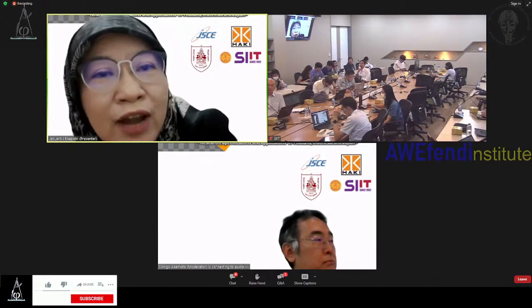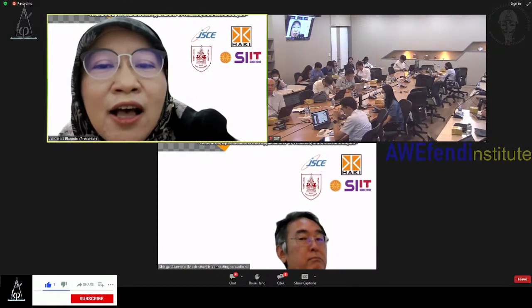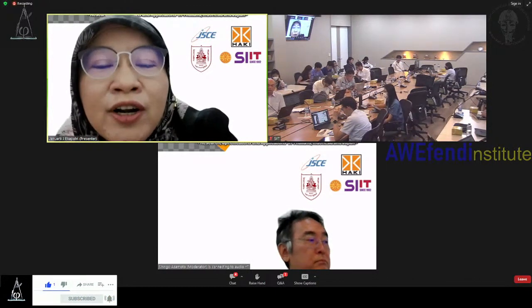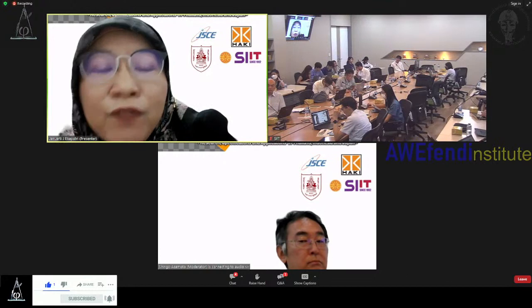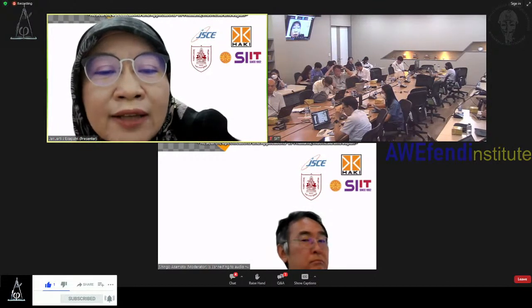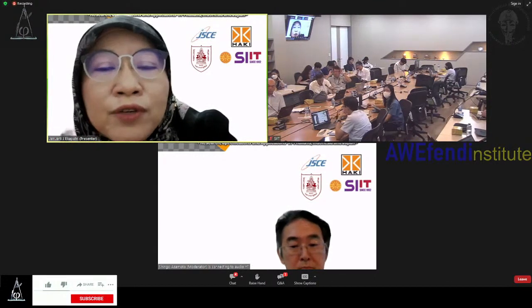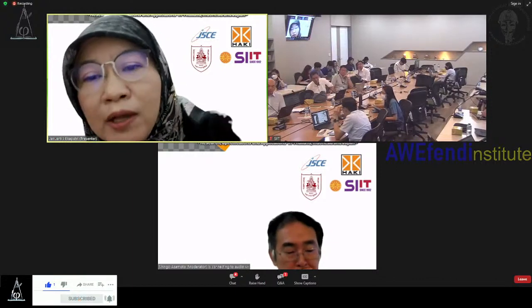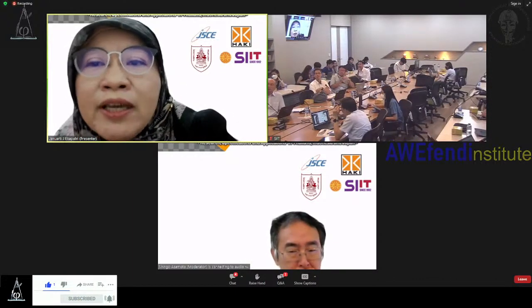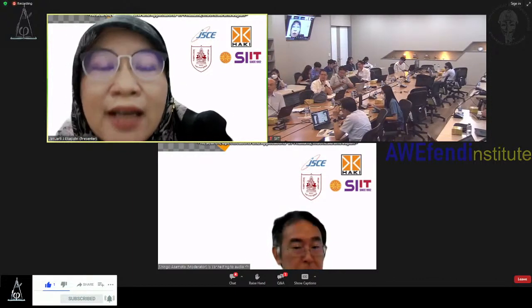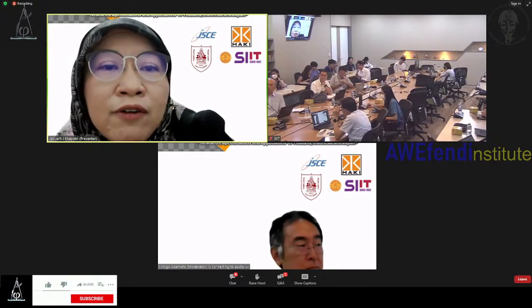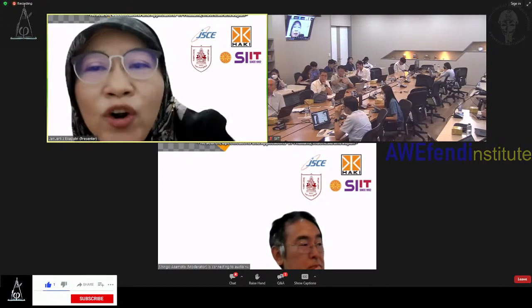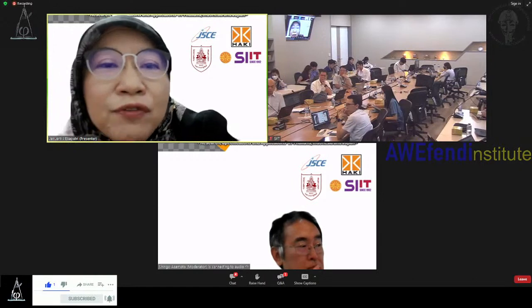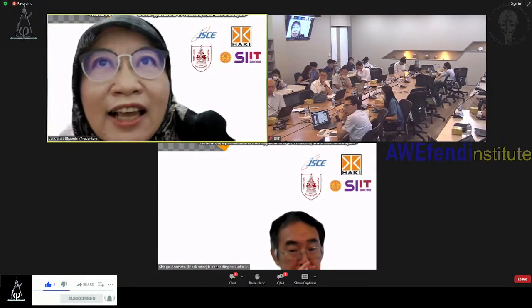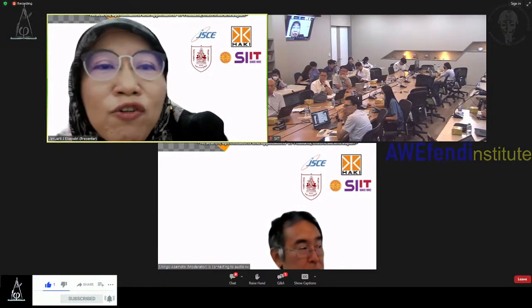So we have to change the sequence. We have to put the fly ash in first, and then the alkali. However, after mixing with the fly ash, sodium hydroxide will dissolve the fly ash and the pH drops. There are a lot of publications and reports saying that the pH of geopolymer is lower than the pH of conventional concrete. I think I have shown it in one of my slides.